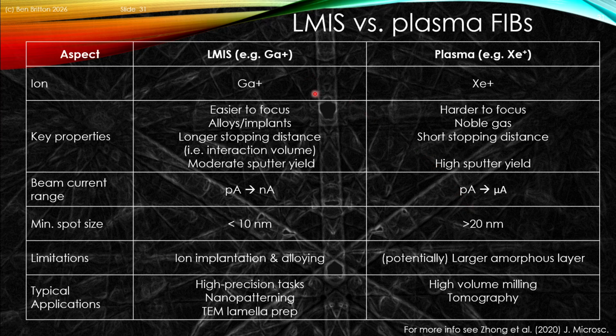There are a whole range of different reasons. We can have this very simple sort of table. This is the liquid metal ion source. This is the plasma source. We can choose, there are of course different ions, as we'll see a bit later. Gallium and xenon are the two we're describing in here. But we have basically that the gallium source, for lots of reasons, is relatively easy to focus. It alloys and can implant. It has a relatively long stopping distance, and that means it controls something about the interaction volume. And it's reasonably heavy, but it has a moderate sputter yield, and so that can reduce the effective cutting rates of this system. We'll typically operate the probe in a picoamp to nanoamp domain, and that's related to the resolution issues, but that gives us some beautifully fine spot sizes, so we can draw or cut with extreme precision in our samples. There are some challenges, as we've mentioned, with regards to ion implantation and alloying of our systems.